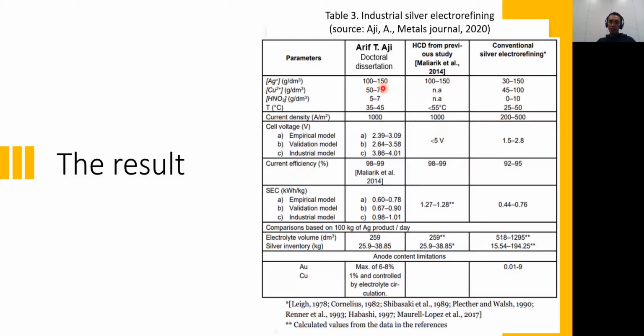I have one publication that proves that there is no copper deposition on the cathode, while in Maliarik's paper it is not mentioned. And for cell voltage, in the previous paper it is mentioned only as less than 5 volts. In conventional electrorefining, it has a lower cell voltage, of course, because they operate at lower current. So it's quite logical. But then my finding from the empirical model is like this.